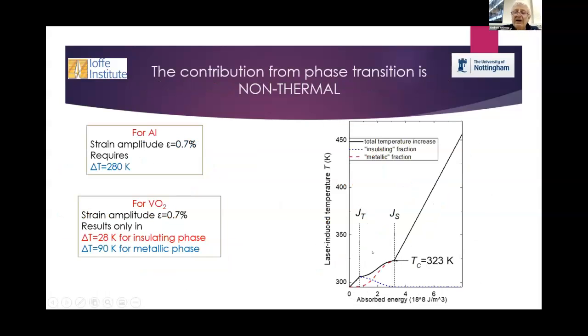So actually, what energy is absorbed, and what is laser-induced temperature, and we see that if the material is in insulating phase, we get this high amplitude strain only for the temperature rising of 28 degrees. So it's comparable, say for aluminum it's 280 K, and here it's only — so it's actually an order of magnitude less heating with the same strain amplitude.